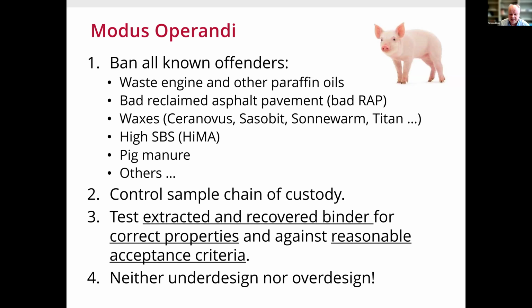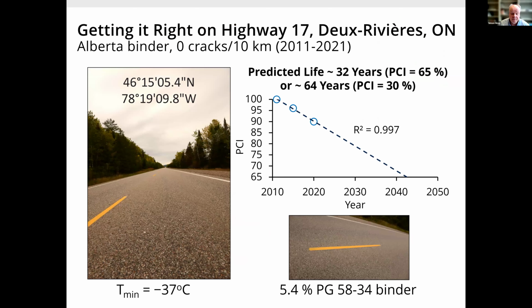You must control the sample chain of custody because samples get mixed up. And you must test the recovered binder. You may also test the tank sample for further information. But if you don't test recovered binder, you're wasting your time. You must use correct properties and you use reasonable acceptance criteria. You neither under-design nor over-design. Getting it right, I put the GPS coordinates on. You can go online, look for it yourself. This is a 10-kilometer contract paved in 2011.